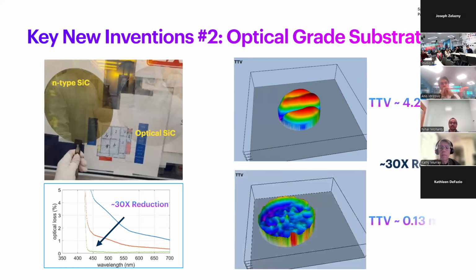New polishing techniques had to be developed that enabled us to reduce the TTV of silicon carbide by 30-fold for enabling optical grade substrates. And it is obvious that diamond was actually used to polish the silicon carbide substrates.